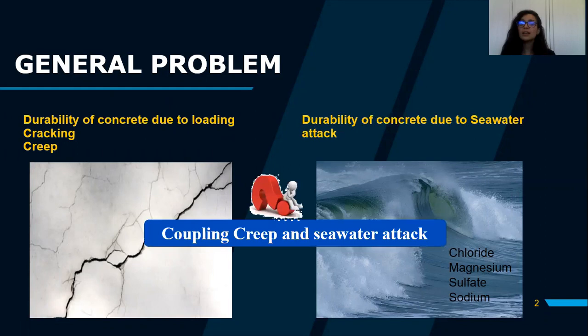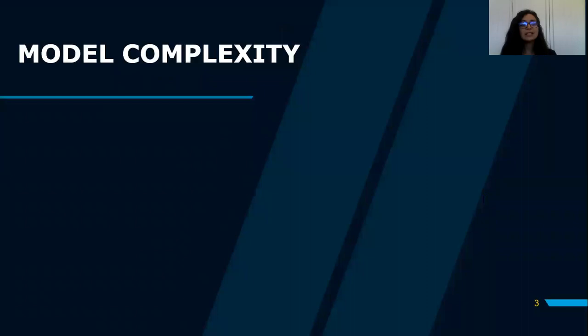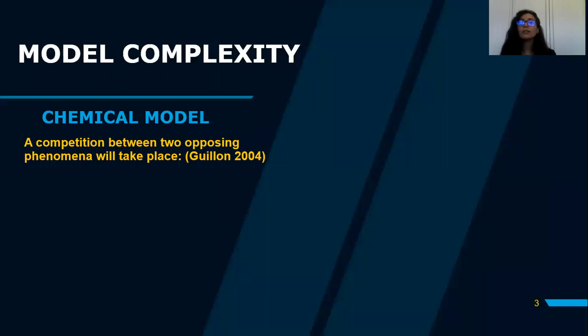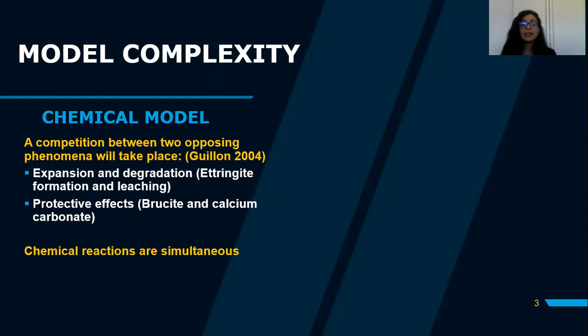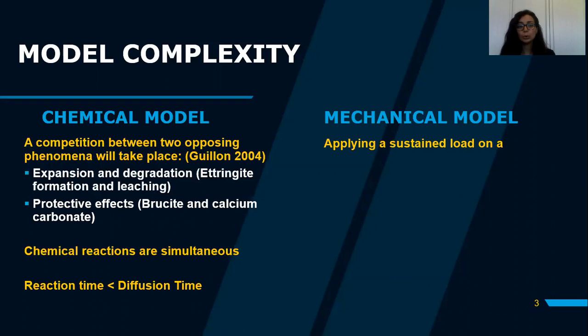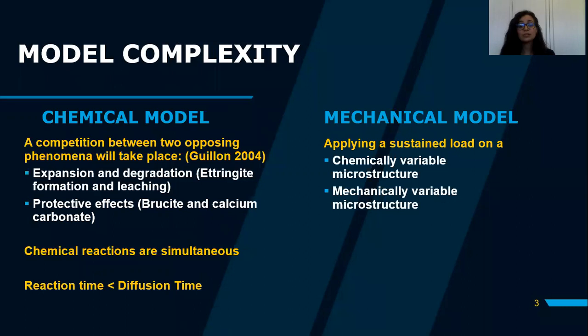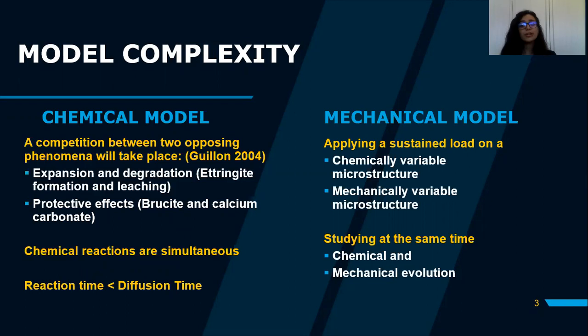Here we are studying the coupling between creep and seawater attack. The model complexity is the following. In the chemical model, there is a competition between two opposing phenomena: expansion and degradation due to ettringite formation and leaching, and the protective effects due to the formation of brucite and calcium carbonate. The chemical reactions are simultaneous and the reaction time is lower than the diffusion time. In the mechanical model, we are applying a sustained load on a chemically and mechanically variable microstructure.